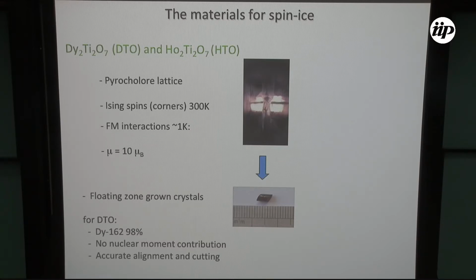So to all extents and purposes, we can think that these are nice Ising spins, but they have a very large magnetic moment. So this idea of just looking at nearest neighbor interactions certainly does not work. You need to take into account that there are dipolar interactions as well. And the nice thing about these two materials is that they're very easy to grow. I mean, you can give a summer student the project of growing one of these, and it works. So you can get really large, nice single crystals of either dysprosium titanate or holmium titanate.